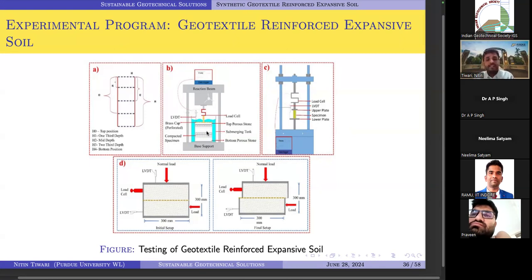The upward swelling pressure test is nothing but this: we submerge the entire specimen and observe what kind of upward pressure is coming from the soil. And we also did the large direct shear, because the small direct shear box is 6 centimeter by 6 centimeter. But we did it with a 30 centimeter by 30 centimeter box, so that you can have a geogrid or geotextile, anchor it and do the test. And this is how we did it.